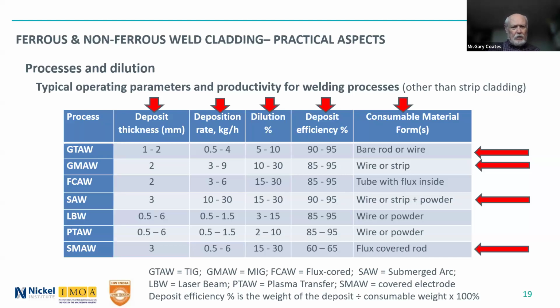But stick welding or shielded metal arc welding is also very useful. And again, you get good deposit thickness, not so great deposition rates normally. Again, highly variable in the dilution, up to 30% dilution. And the deposit efficiency is low, but it is good for small jobs.